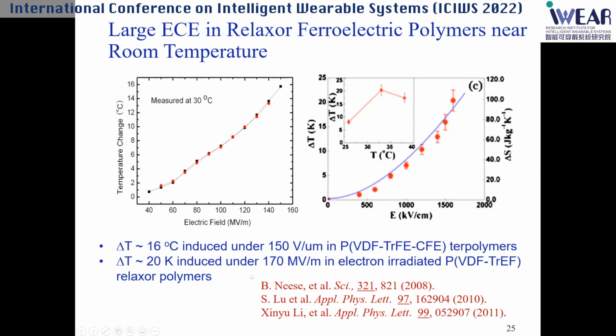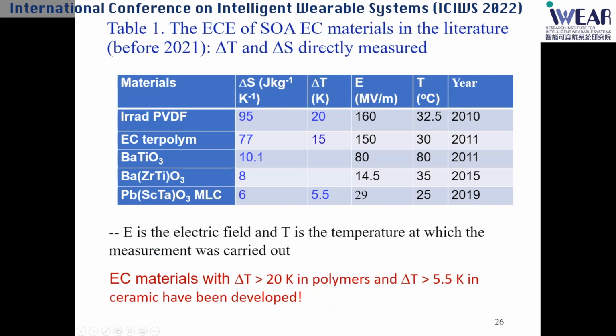So here's a summary of the state of the art of electrocaloric materials, which have been studied over many years after 2008. If you look at the literature, there are a lot of reports of bigger numbers, but many of those values aren't so convincing. So these are the EC values that are directly measured. You can see the temperature change is 20 Kelvin, 15, and as I said, there are composites which can get about 40 Kelvin. So basically this table shows that EC materials with temperature change more than 20 Kelvin in polymers and 5.5 Kelvin in ceramics have really been developed. With these values, people could work on many EC devices.